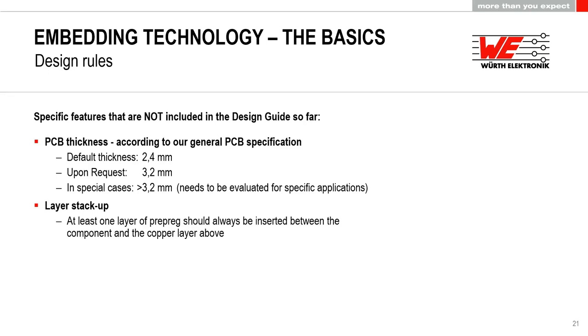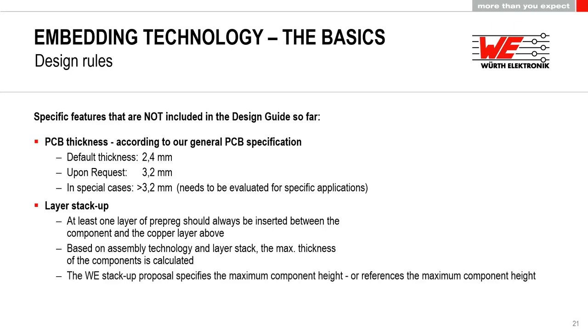The layer stack-up. Well, at least one layer of prepreg should always be inserted between the component and the copper layer above. This is due to isolation requirements, so that the component is not directly in contact with the copper layer above if something happens during lamination. And based on the assembly technology and the layer stack, the maximum thickness of the components can be calculated.